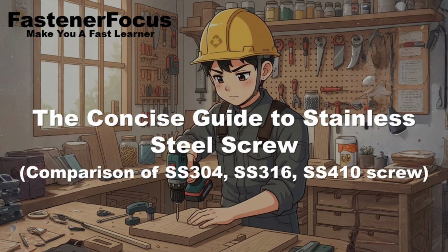Now let's pivot to 410, the martensitic grade 410. It operates in a completely different metallurgical landscape. Completely different. Grade 410 belongs to the martensitic family. Unlike austenitic steel, 410 contains minimal nickel, less than 0.75%, but it contains higher carbon content. This composition allows it to achieve high strength and hardness through the traditional heat treatment process involving quenching and tempering.